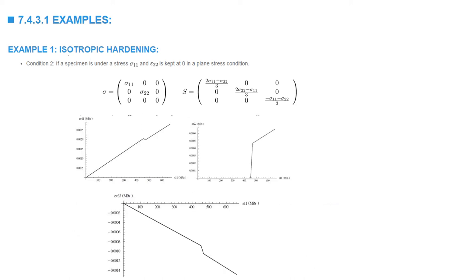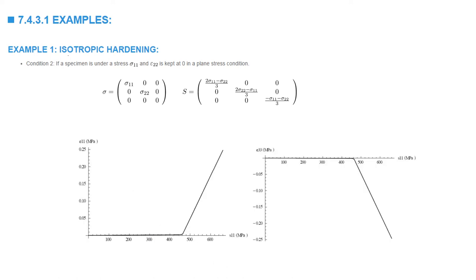The elastic strain in direction 2 versus applied sigma_1 shows that before plasticity, the condition epsilon_2 equals zero leads to zero elastic strain in direction 2. Once plasticity initiates, a tensile elastic strain develops in direction 2 to compensate for the permanent plastic compressive strain, since the total strain (elastic plus plastic) must remain zero. The total strains epsilon_1 and epsilon_3 change with applied loading consistent with the bilinear stress-strain curve.